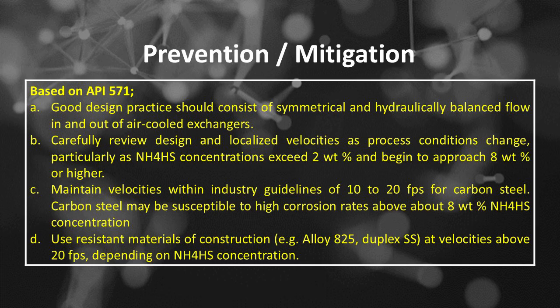Number A, good design practice should consist of symmetrical and hydraulically balanced flow in and out of air-cooled exchangers. Number B, carefully review design and localized velocities as process conditions change, particularly as NH4HS concentrations exceed 2 wt% and begin to approach 8 wt% or higher. Number C, maintain velocities within industry guidelines of 10 to 20 feet per second for carbon steel. Carbon steel may be susceptible to high corrosion rates above about 8 wt% NH4HS concentration.